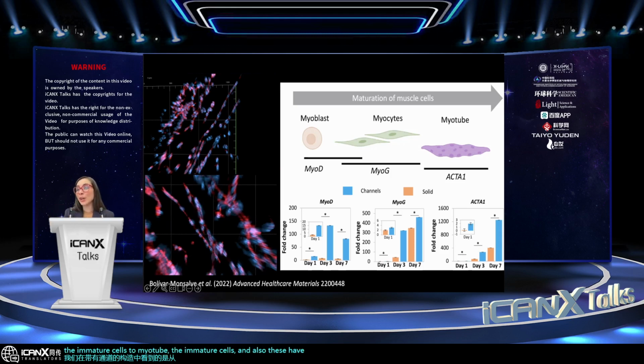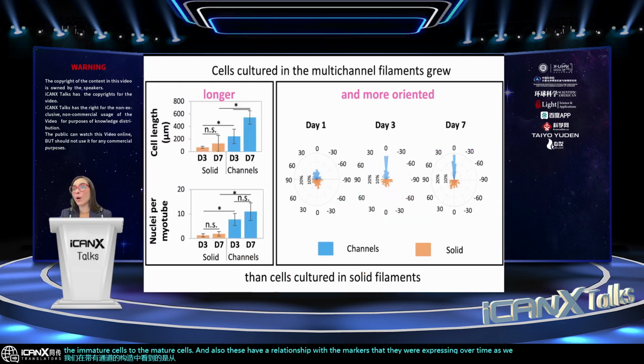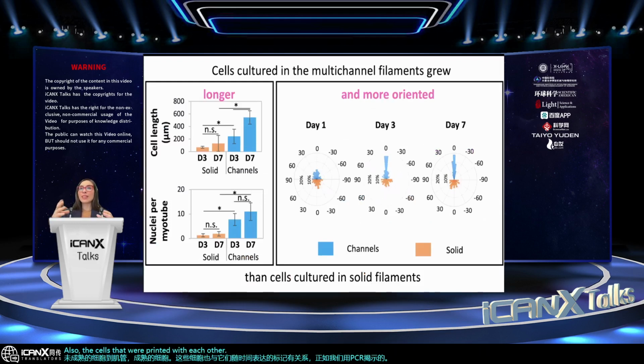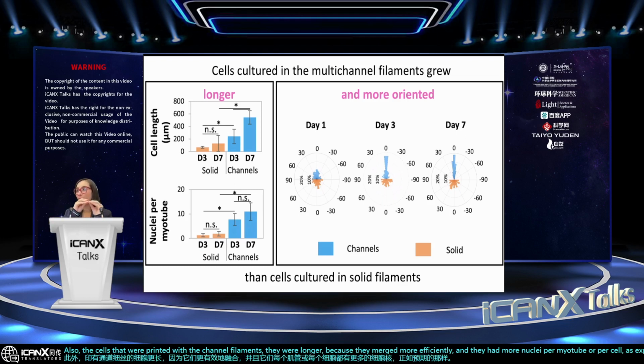And this had a relationship with the markers that they were expressing over time, as we revealed with PCR experiments. Also, the cells that were printed with the channel filaments were longer because they merged more efficiently, and they had more nuclei per myotube, as expected. And very nicely, they were also more oriented towards the main direction of the filament.